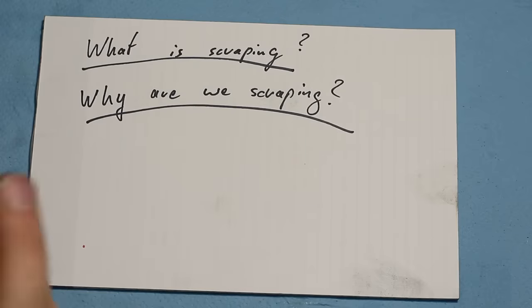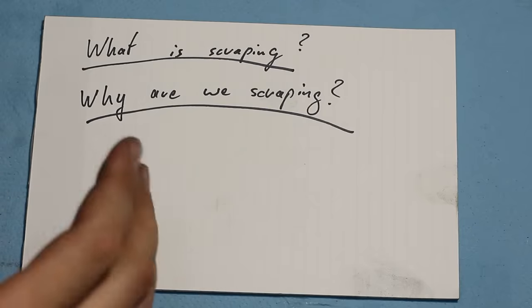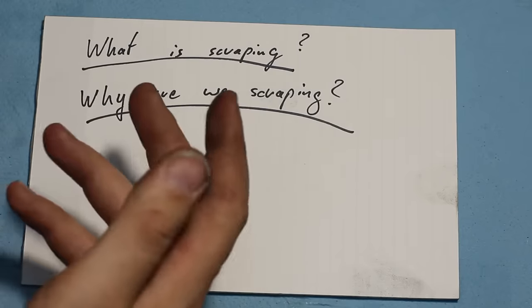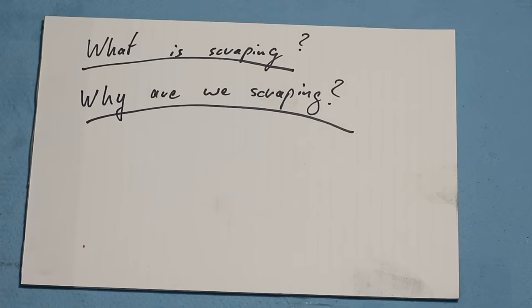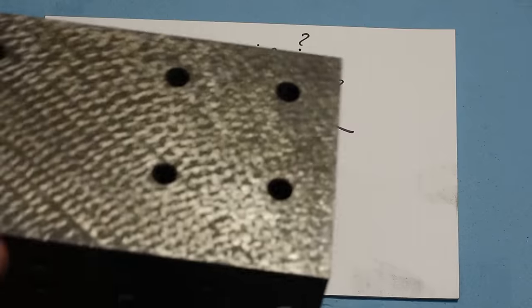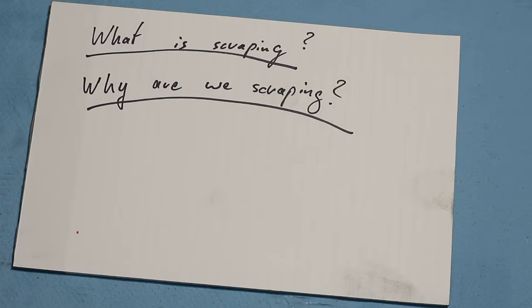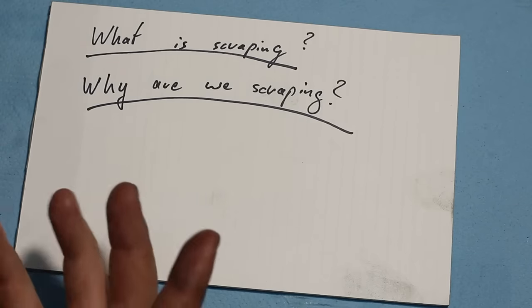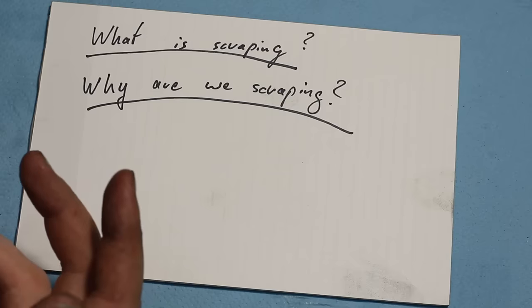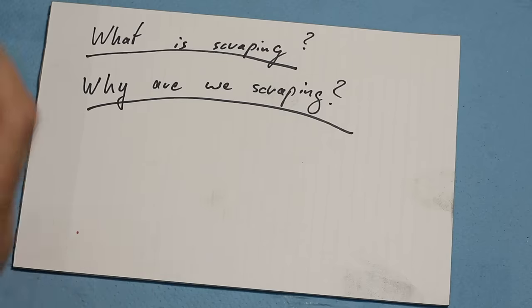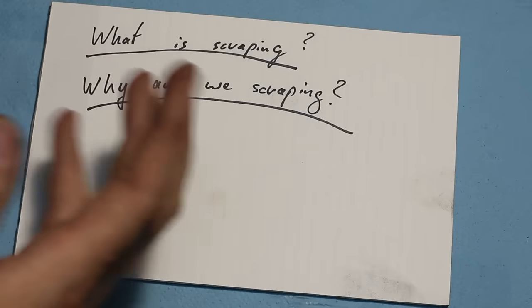There are two kinds of surfaces you want to scrape. One: sliding surfaces, like machine ways. On those, the scraping is beneficial because it doesn't give a uniform even surface — it creates a pattern of high and low areas, which is beneficial to carry oil between the two sliding surfaces, which prevents galling and premature wear. On the other hand, there are surfaces that you scrape because you have no other way to create a flat surface — maybe for an angle plate like this one. You could surface grind it if you had a big enough surface grinder, but if you don't, you machine it and then scrape it. On those parts you don't want heavy deep valleys for oil, because they are not sliding parts — you just want the part to be flat.